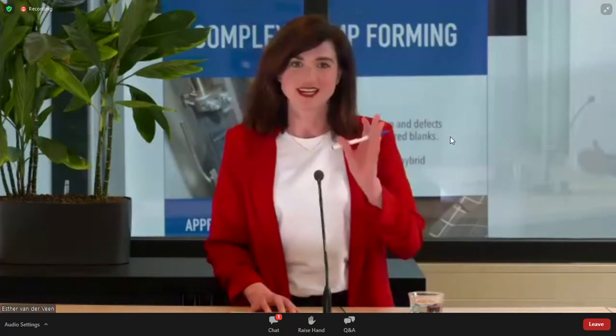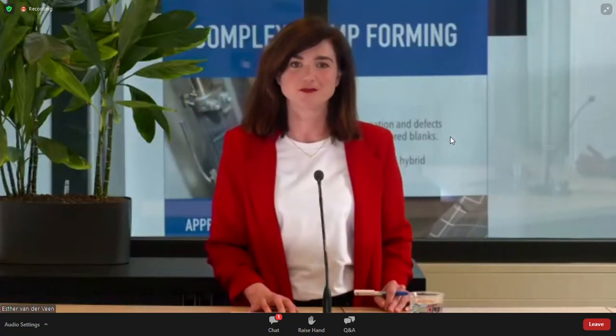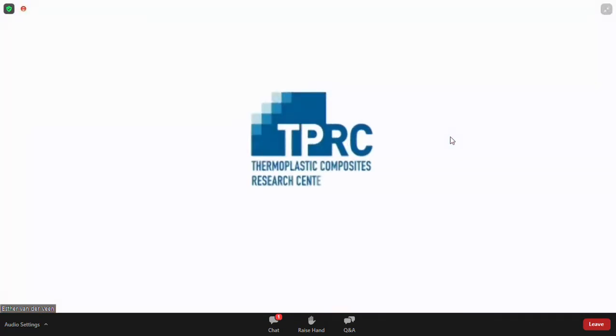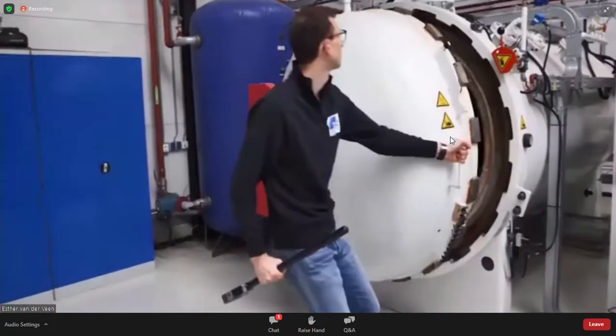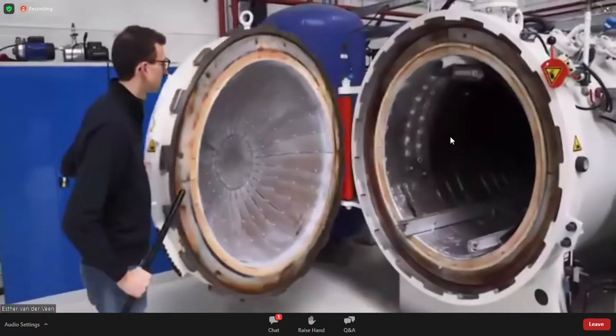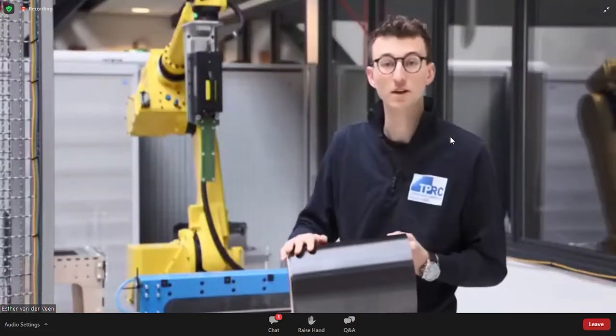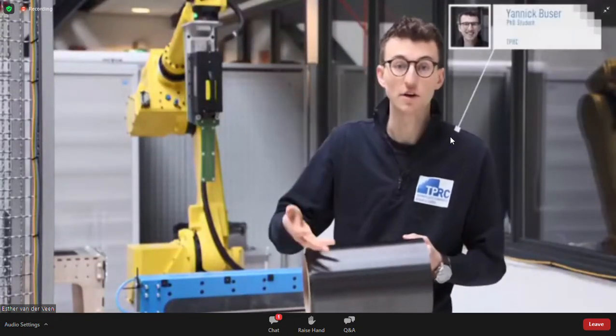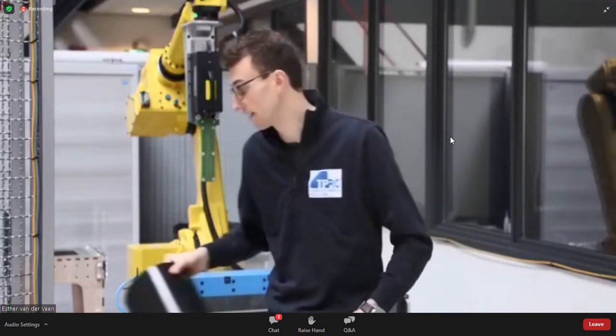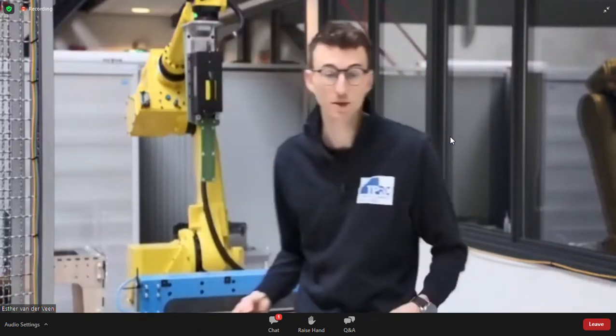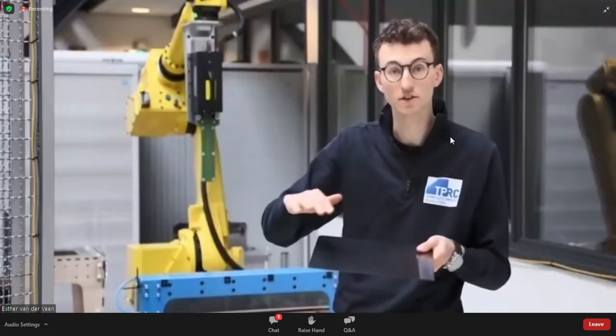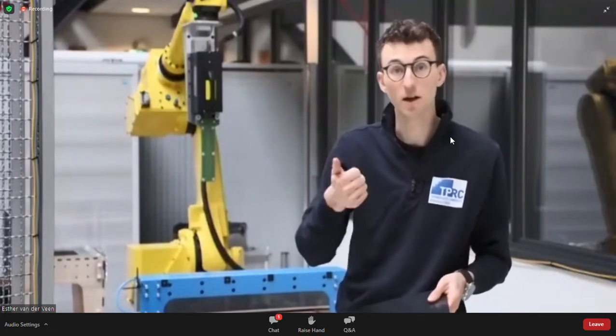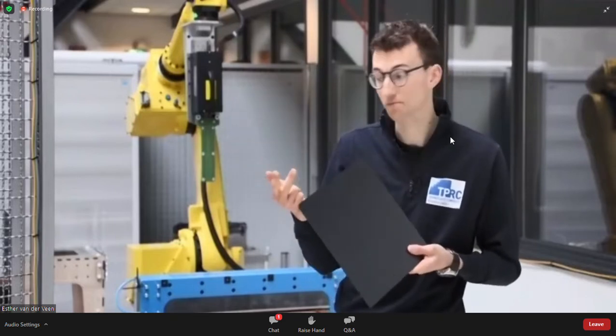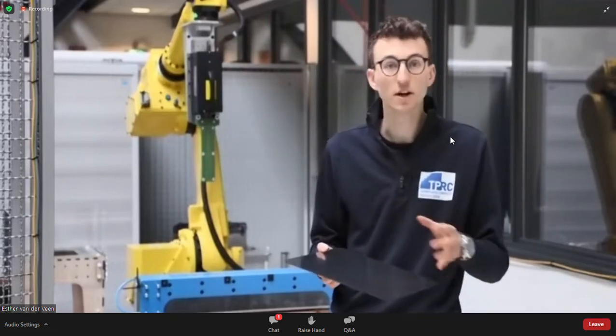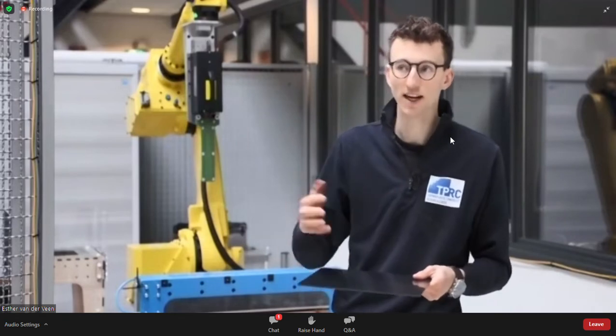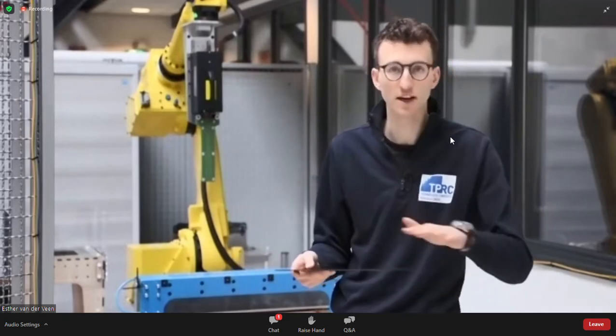First things first, Yannick Buser, how does welding work? In our typical manufacturing process for thermoplastic composites, we take tape from the manufacturer as input material, where we cut it to size and we stack it. And then in an autoclave or a press, we typically fuse those different layers of the stack together with the right time, temperature, and pressure. And what we do here is we apply this temperature globally by bringing the entire stack into melt, where all those layers are fused together in the end.